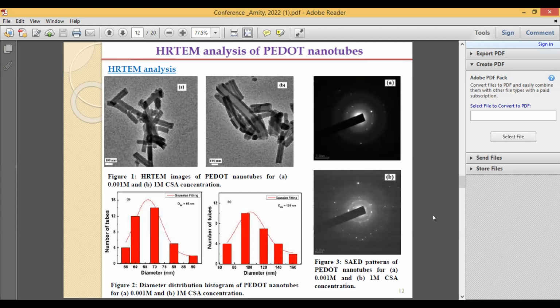Then we have also done the SAED pattern, and the SAED pattern shows a diffuse ring in both the samples, which confirms the amorphous nature of the material, and the presence of ring spots and white dots signifies the semicrystalline nature of the material. That means the presence of both the diffuse ring as well as the white spots suggests that it's of semicrystalline nature.